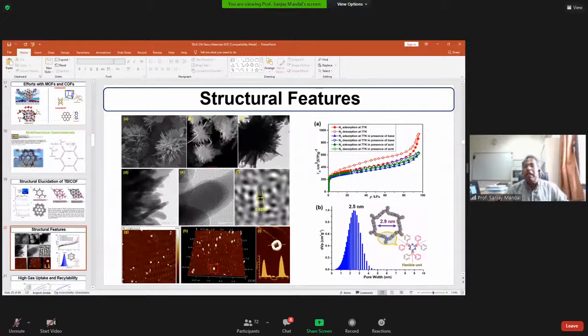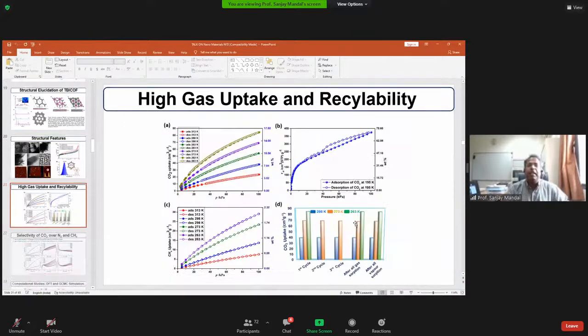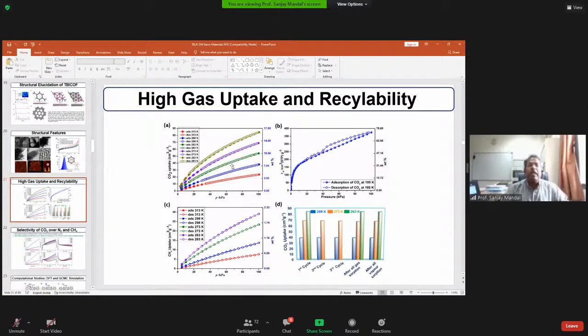And we have done the nitrogen adsorption, and you can see that at 77K, which gives you this surface area value. And then we also tested its stability in base and acid. It didn't decrease much. From this, we know that the pore width is 2.5 nanometer, and from the structural analysis, we know it came about 2.9, which is very close to the experimental value. This is what I was talking about, that nitrogen adsorption is the real data when the theoretical value can give you something, right? So we then look at the gas adsorption, CO2 here,